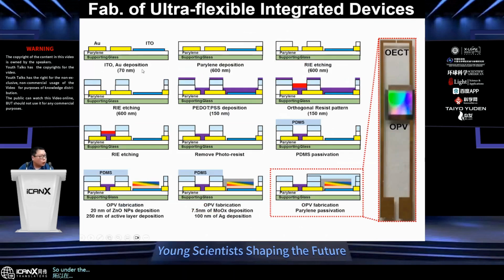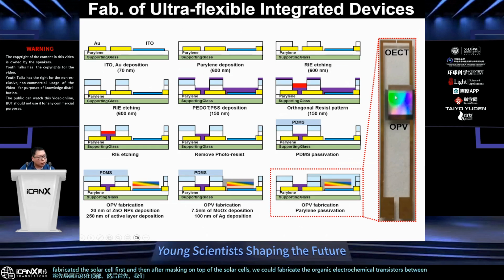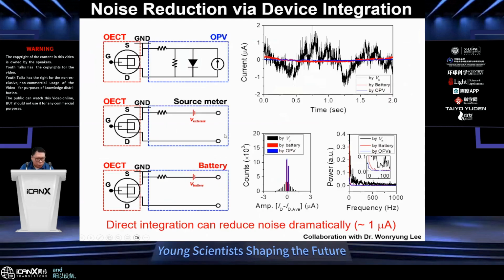This is the way we could integrate the devices. On the supporting glass substrate, we deposited the parylene layer on top, and then firstly we fabricated the solar cell, and after masking on top of the solar cells, we could fabricate the organic electrochemical transistors between the source and drain gold electrodes. On the right side, you can see the finalized devices. And the most important point is that by integrating those devices together, we could extremely minimize the noise signals when we measure those signals as a function of time.